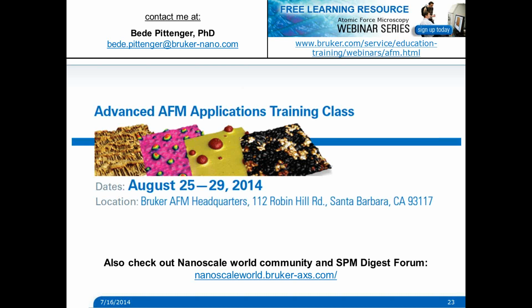Now, there was a question earlier on the DMT model and the effect of adhesion in your modulus measurement. Bede, did you want to say something to that? Yeah, the DMT model is a very simple approach to the calculation of modulus, and it does include adhesion. It doesn't specify where that adhesion is coming from, and it is one extreme of the way of possibly treating adhesion in the measurement.